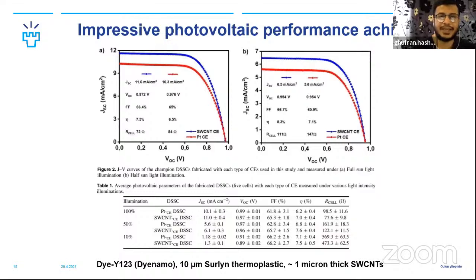When I fabricated these devices and tested them under both full sun and half sun light intensity, you can see a very impressive more than 7% efficiency achieved under full sun with the champion device, and under half sun we achieved more than 8% efficiency. That was one of the very eye-opening results compared to the traditional platinum. As you can see, far lower performance was achieved with the traditional platinum catalyst.